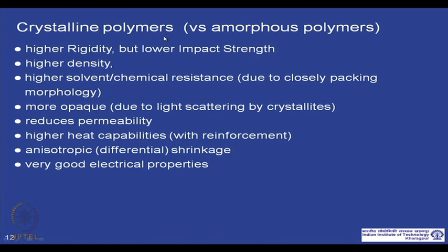This is not all desired. You should not have the perspective that all crystalline or semi-crystalline polymers have better properties than amorphous polymers. They have some better properties, but at the cost of something else, like they always become opaque or translucent. If you want applications where you need a transparent polymeric material, then it is very difficult to do with crystalline polymers. You always end up choosing an amorphous material. So, there is always a balance between what you need for the final applications.